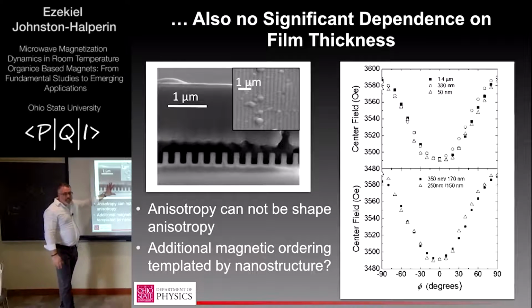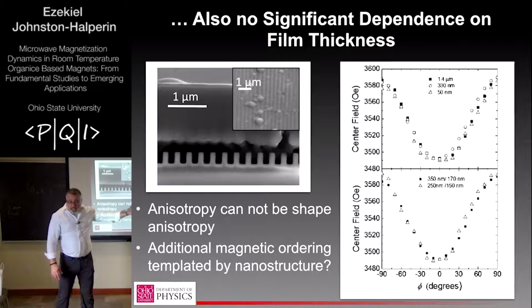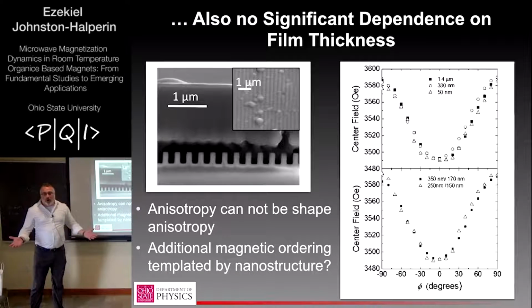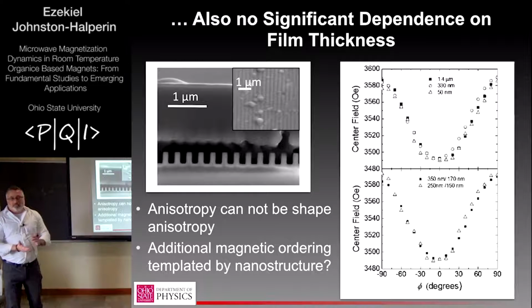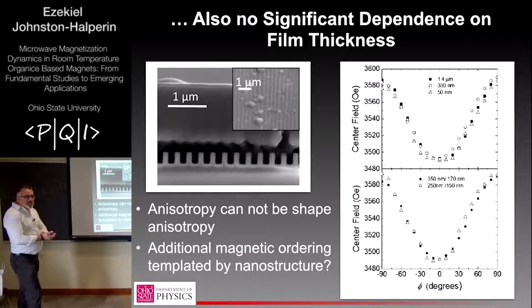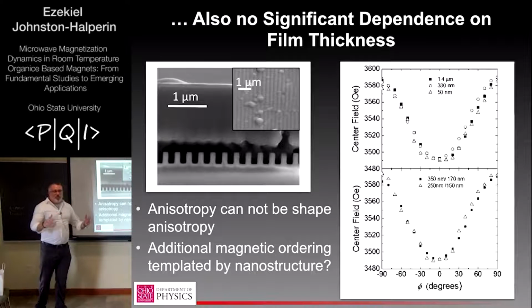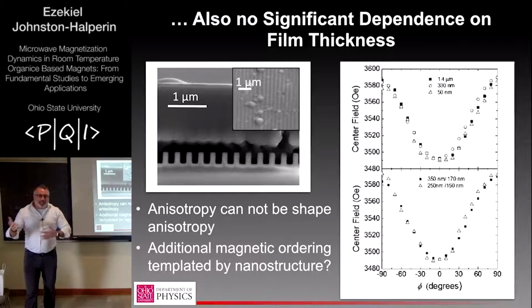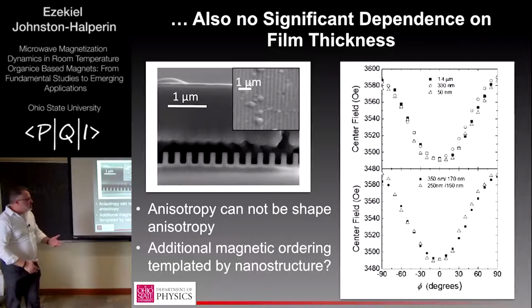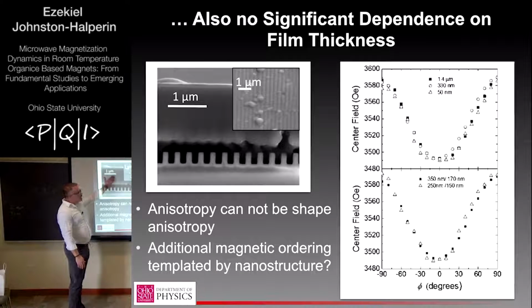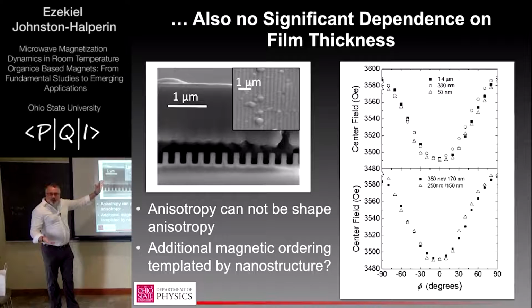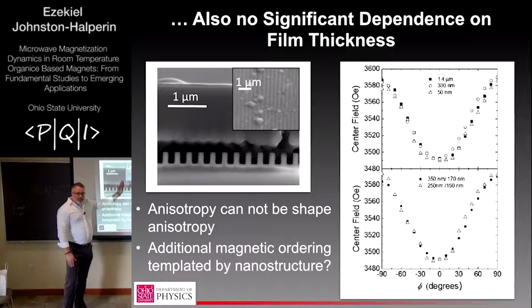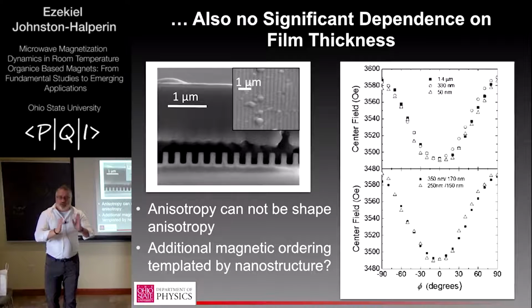So what this means is this anisotropy is in fact not shape anisotropy. And really there's only one candidate left, and that's some sort of crystal field anisotropy. So coming back to the very beginning of the talk when I was discussing crystallinity or lack thereof of these systems, the only way we can be getting in-plane anisotropy out of this film is if there's some preferred molecular ordering. And that ordering is not there in a uniform thin film deposited on a flat substrate. So something about these interfaces is templating some order.